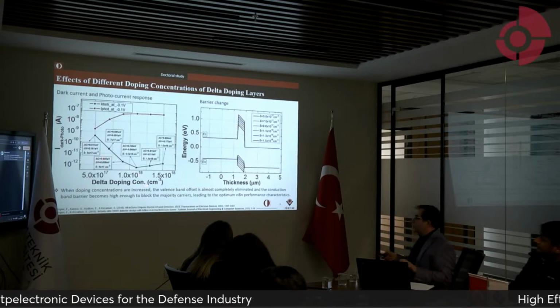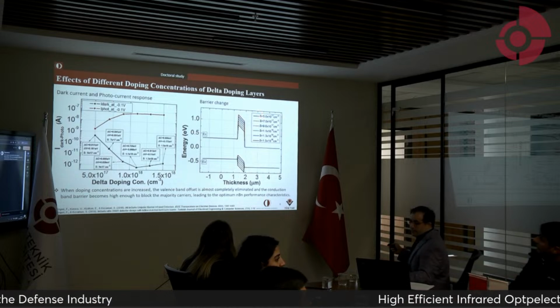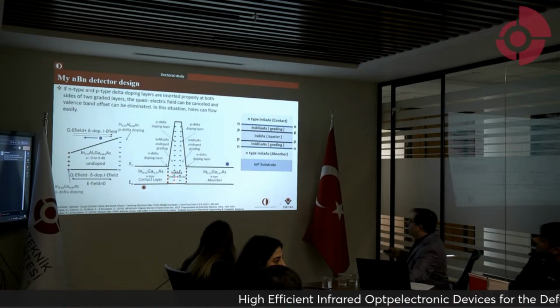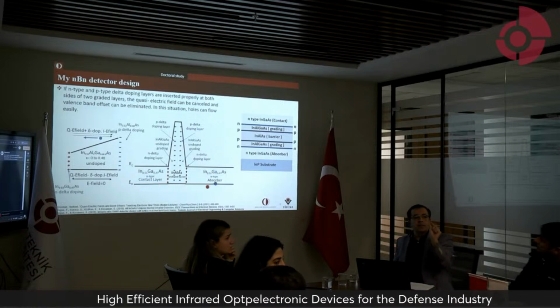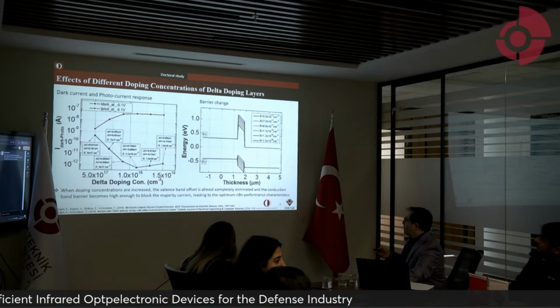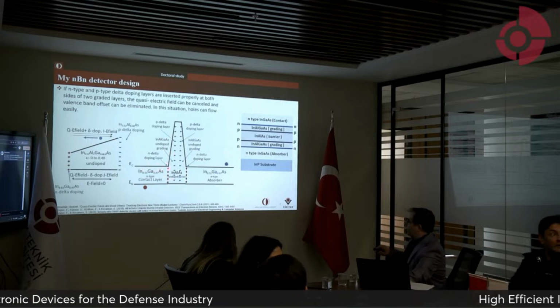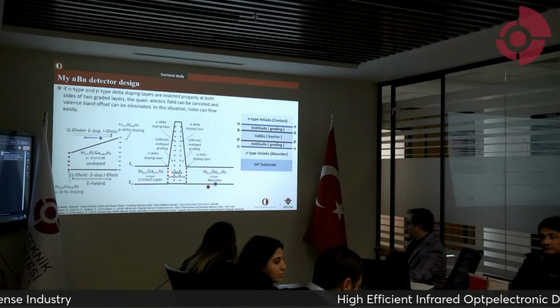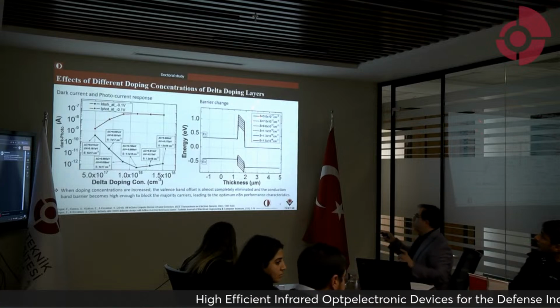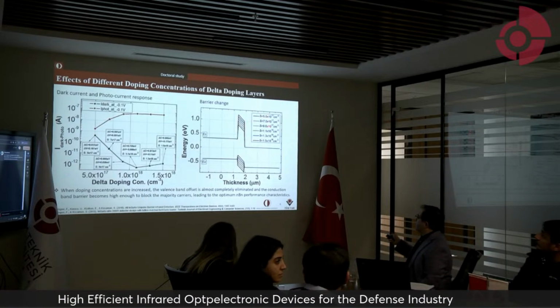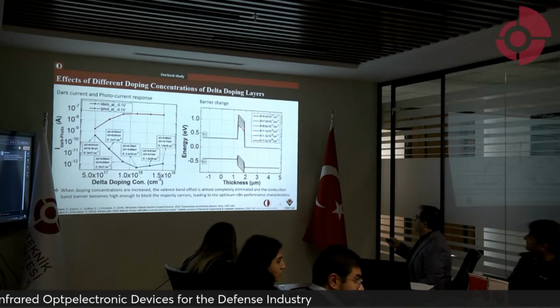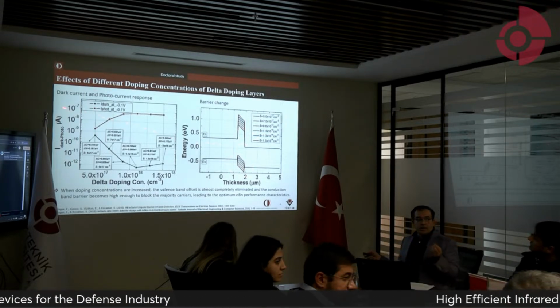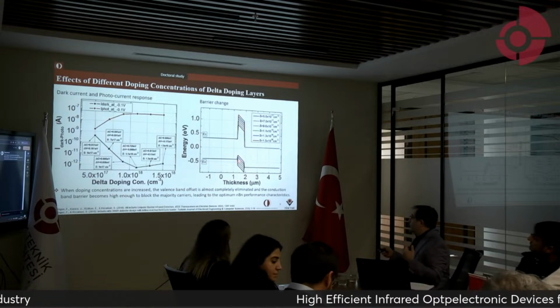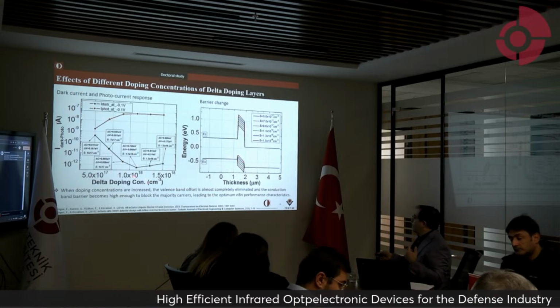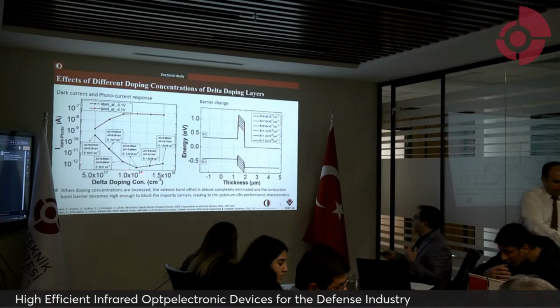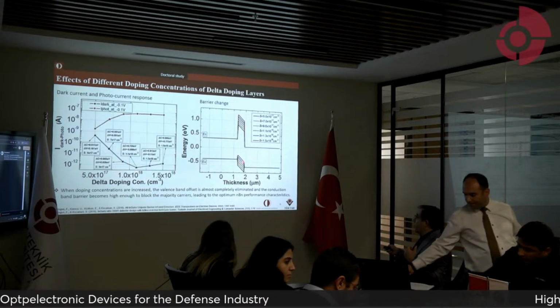This is my simulation. You can see the delta doping layers. Delta layers are very thin semiconductor layers. If you insert them on both sides of these graded layers, you can cancel the valence band discontinuity. In my simulation, when I increase the doping concentration of the delta layers, the valence band discontinuity gets smaller. You can see the most optimized concentration is this, and the valence band almost disappears.